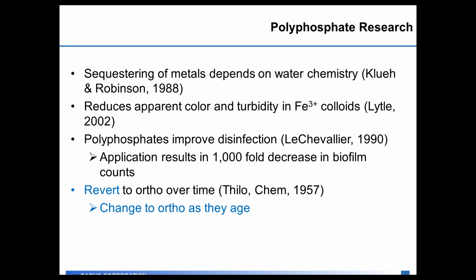One thing that all polyphosphates do over time is they're going to revert from polyphosphate to orthophosphate. So one of the things to keep in mind if you're feeding a polyphosphate or a blended phosphate product that includes poly is that they do have a shelf life of 6 months to 1 year because that polyphosphate is slowly going to revert to ortho over time.